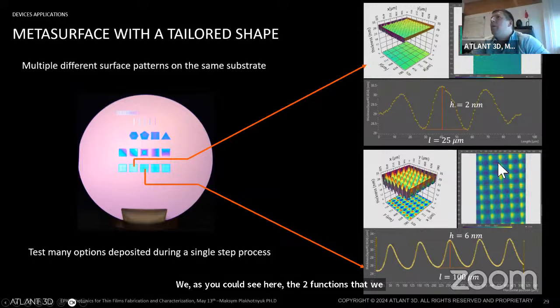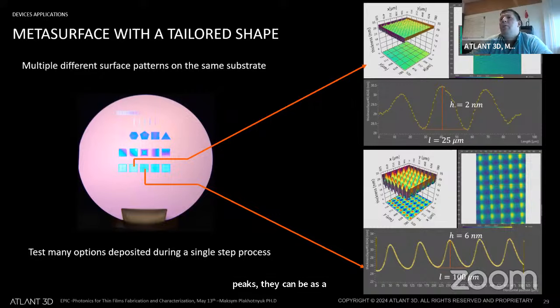Another very interesting test that we did: metasurface and surface modulation, basically. As you could see here, there are two functions that we implemented. One has this type of shapes, I don't know how to call them. Another was with just peaks. They can be even as well as uneven, and it really depends on the geometries. And again, this is in automatic mode. We did these measurements with imaging ellipsometry just to confirm that we obtained what we expected.